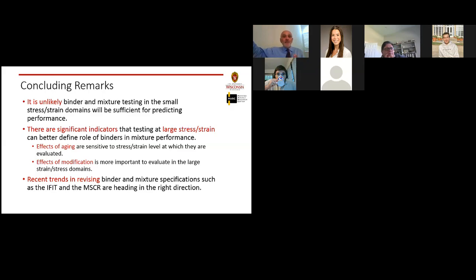That steady state, I am very, very confident, you will find a very good correlation to the wheel tracking. So unfortunately, in the development of the MSCR, this portion of reality of getting to the steady state was not a focus, and they just missed it. So the original proposal was the MSCR should contain hundreds of cycles at two strain levels, not 10 cycles. And as you know, very recently they modified the test. Now we have to run 20 cycles before you run the 0.1 and then you run the 3.2. If you take the MSCR and take 100 cycles instead of 10 cycles, you will reach the steady state.